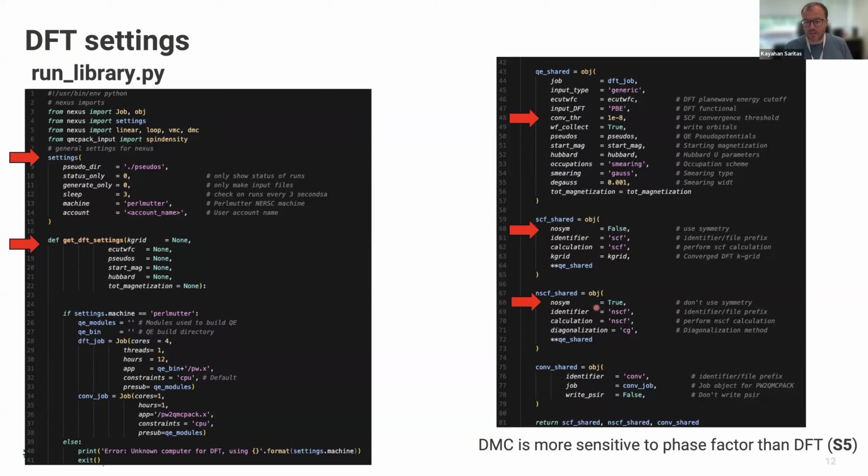Sometimes, depending on the symmetry of your calculation, if you enable the symmetry, the phase of your wave function at certain k points might be mixed or interpolated, as you calculate k points that can be formed using symmetry. For example, an area where this caused me an issue previously was when you want to calculate the formation energy of graphene, and if it happens that your twist grid is crossing the Dirac point, you will see some kind of degeneracy.